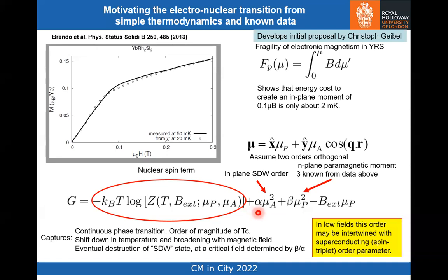Clearly, alpha is smaller than beta, so that the cost of forming spin density wave order is smaller than forming paramagnetic order. Okay, so this of course leaves a lot of things out. One of the things that it leaves out is that at low fields, this order that we're discussing may be intertwined with the superconducting order parameter, which I'm going to argue is spin triplet.